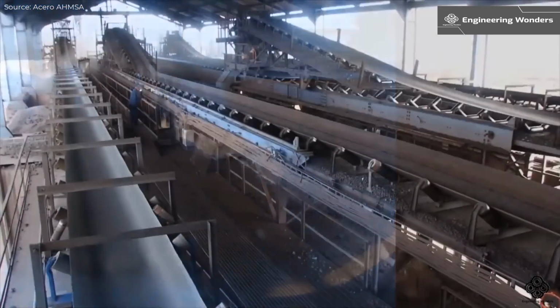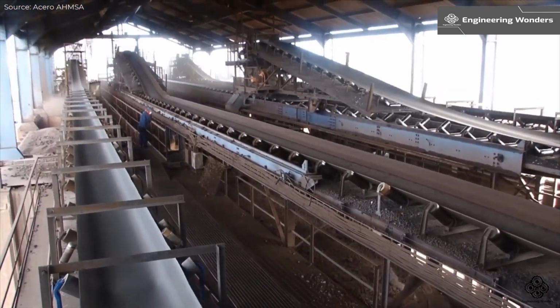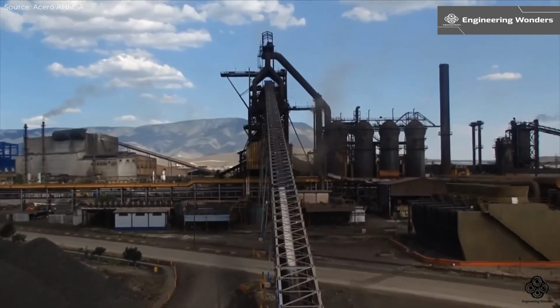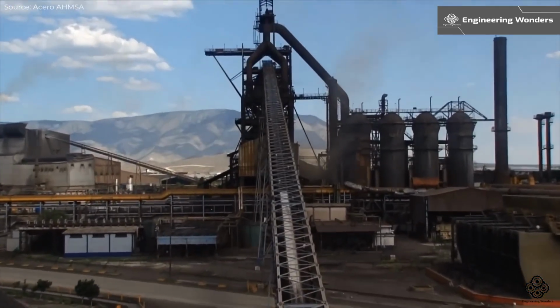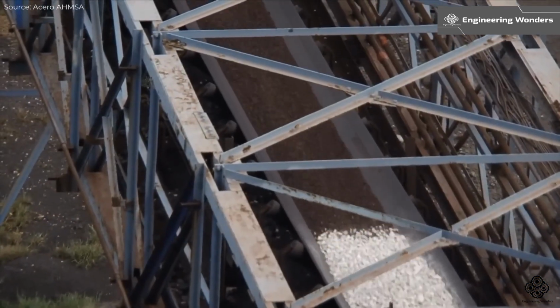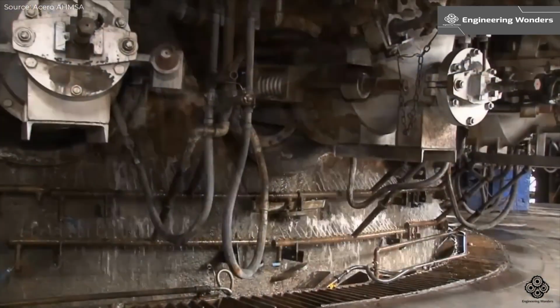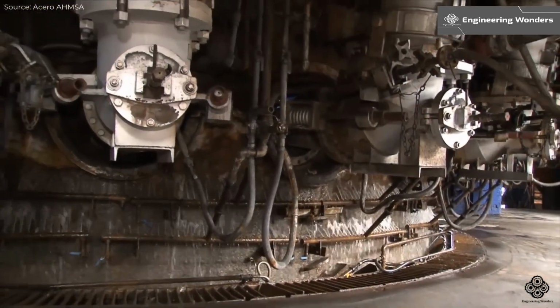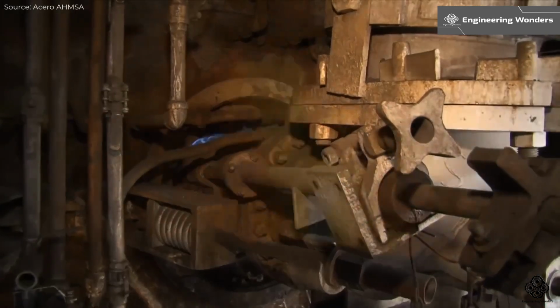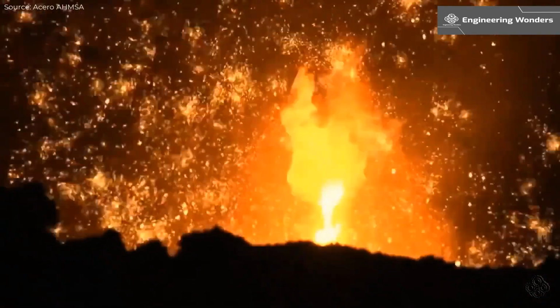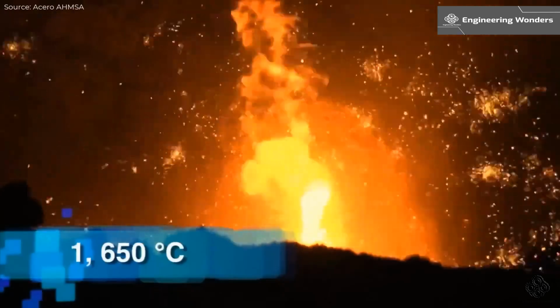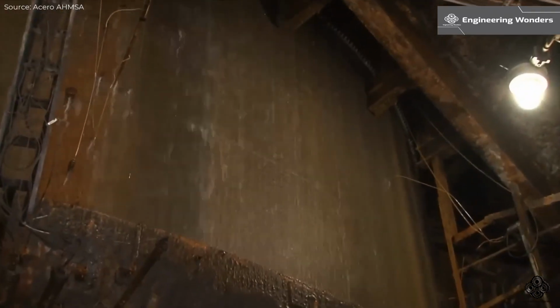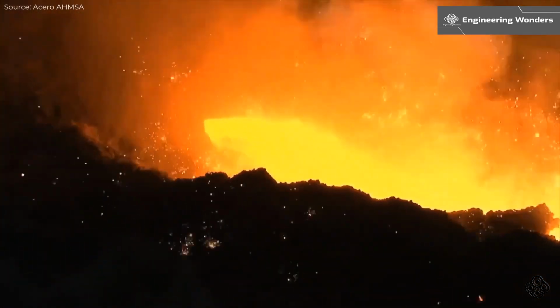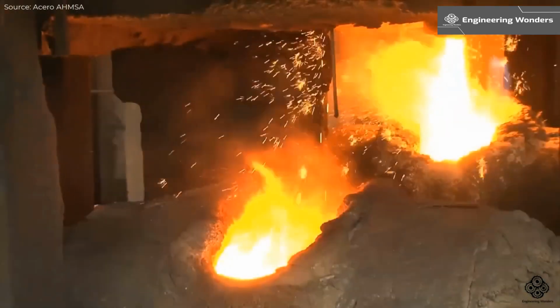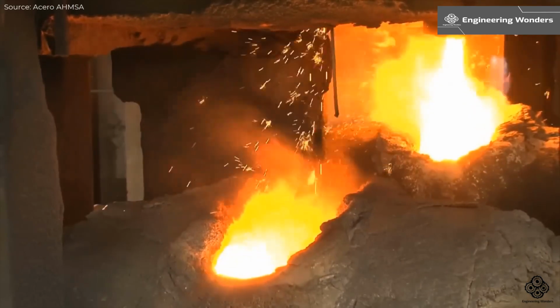Charging the furnace. Raw materials such as pellets, sinter, limestone, dolomite, and coke are stored in hoppers and deposited into the blast furnaces through a charging system located at the top. Smelting. Hot air, introduced under pressure at the furnace's bottom, blasts the coke and smelts the iron ore at temperatures up to 1,650 degrees Celsius. The molten metal collects in a graphite hearth at the furnace's base and is then drained through tap holes into 200 metric ton capacity torpedo cars.